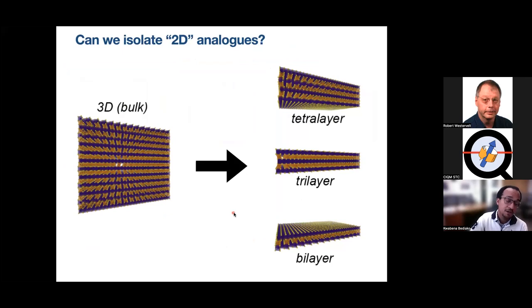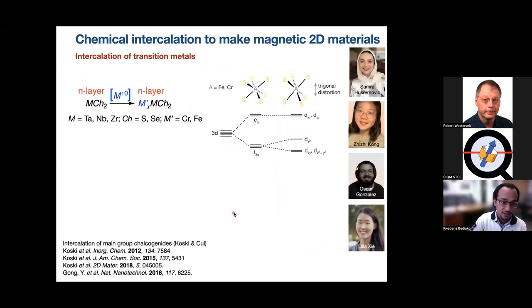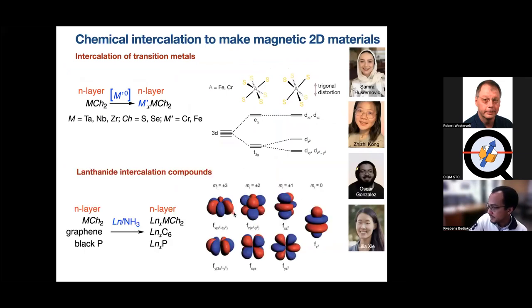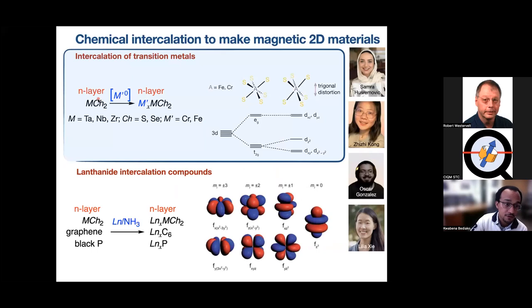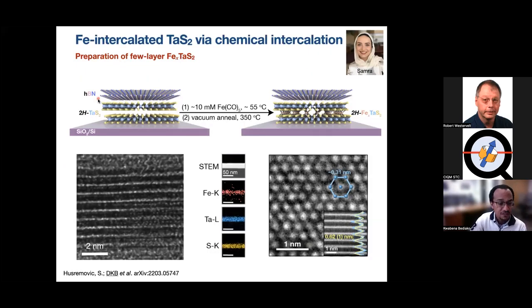And so one question we wanted to know is, can we isolate 2D analogs of this family of materials? It's very, very difficult to exfoliate them down and get to very thin layers, because once they're intercalated, they're basically bonded. The layers are bonded together. So instead, what my group uses is we start out with the neutral parent layers that are van der Waals bonded, and then we use chemical intercalation to insert transition metals between the layers. And lanthanides as well, but I'll talk mostly about the transition metal case.